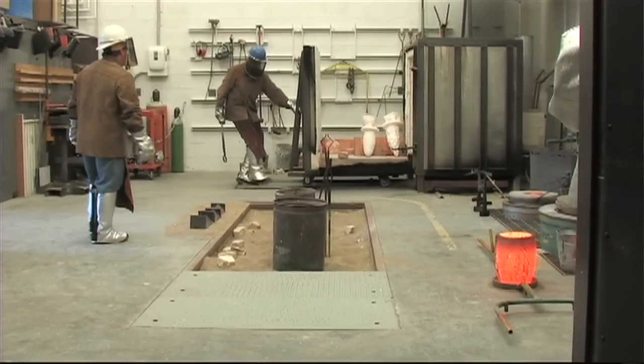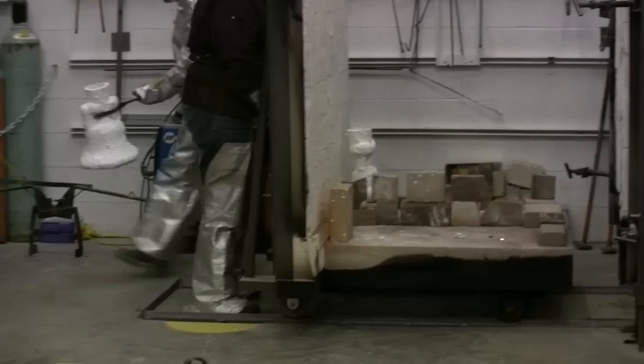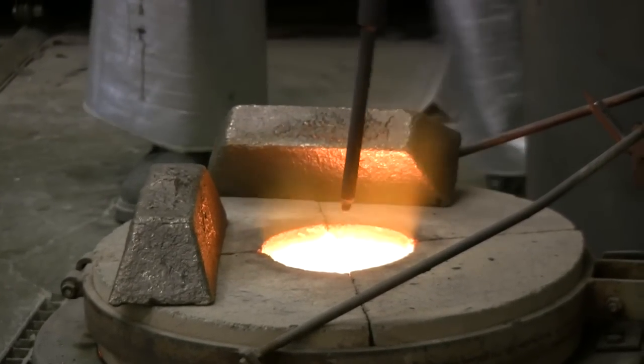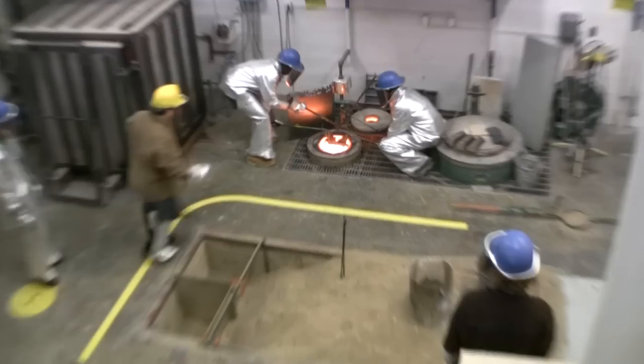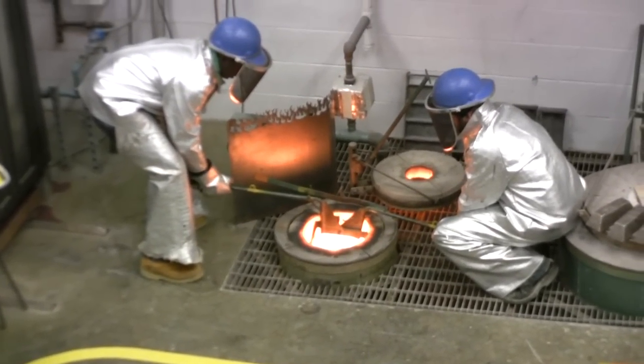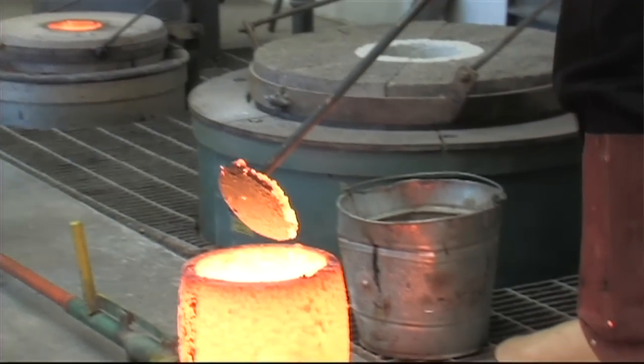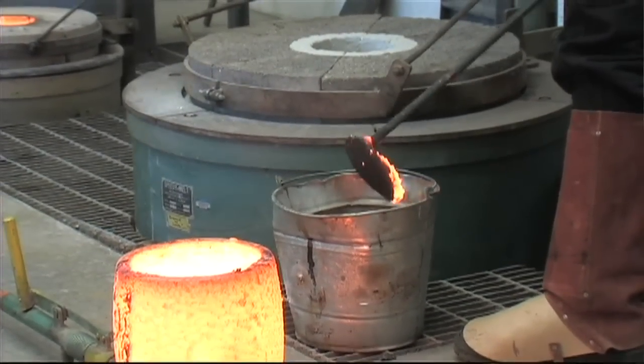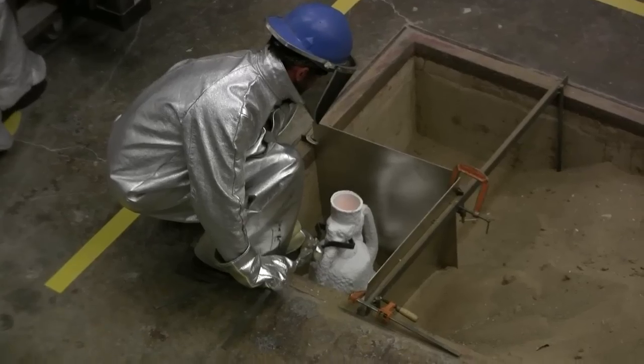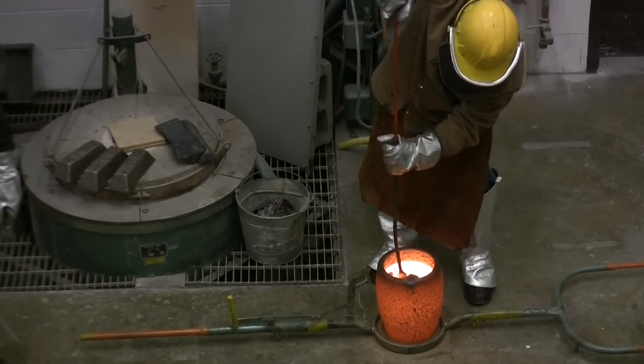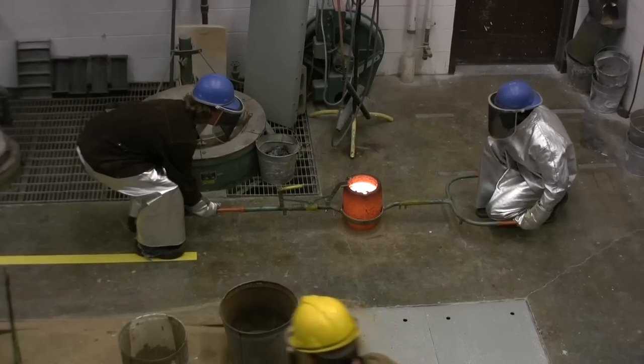This is where we do the burnout. We take your ceramic mold with the wax burnt out, we reheat that, and at the same time melt a pot of bronze in a blast furnace and take that up to liquid at about 2,200 degrees Fahrenheit. When the molds are at temperature, the metal's melted, and we know the metal's hot enough to pull out, this beautiful little dance starts.